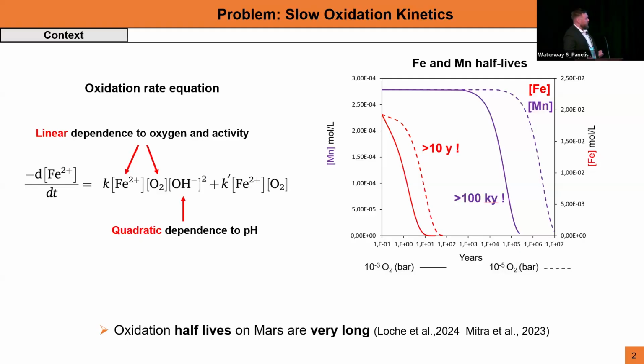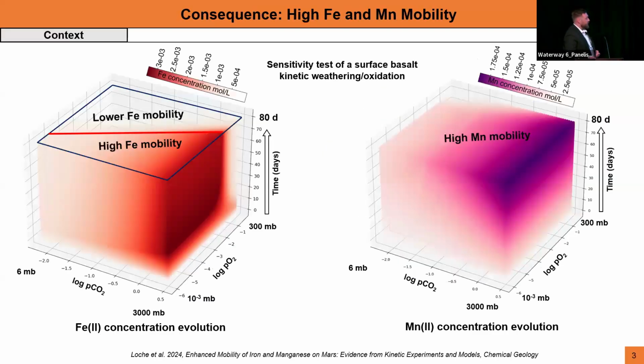And the first observation on that is that we checked last year with a paper that indeed manganese and iron are very mobile in a lot of conditions. So this is the result from a sensitivity test of basalt weathering. You have a basalt under CO2 being weathered, and we tested a lot of different partial pressures of CO2 and of oxygen. And what you see here is basically the concentration.